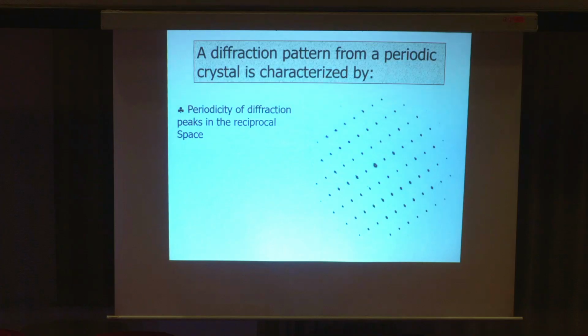Now let's go to the reciprocal space. This is the space in which the diffraction exists. But I will not show you X-ray diffraction. I'll show you electron diffraction taken by a transmission electron microscope. And here is a diffraction pattern from a periodic structure, not quasi-periodic material. And you can clearly see that the real space and the reciprocal space are similar in several ways. Number one, each dot here is not an atom. This is a diffraction spot.